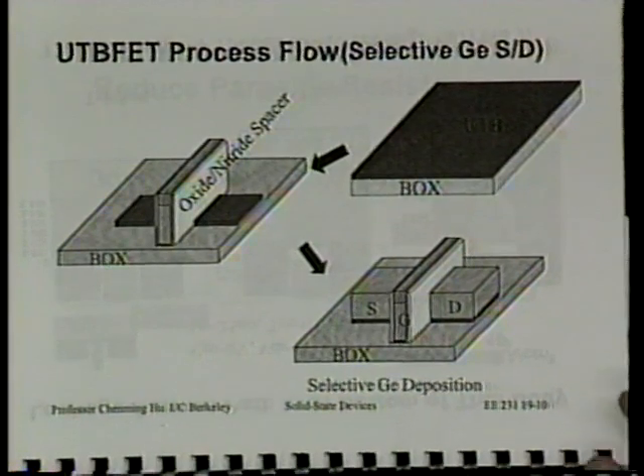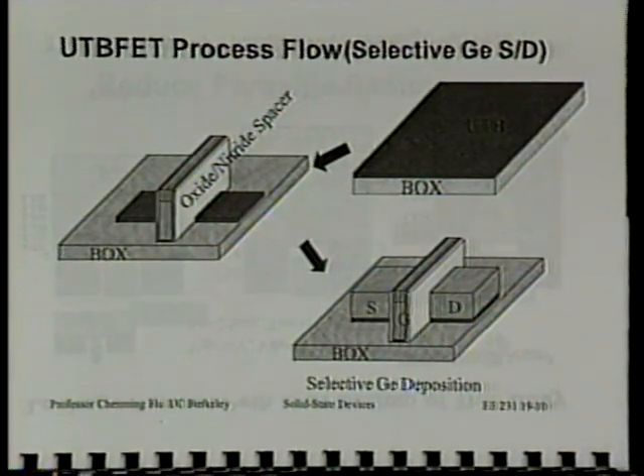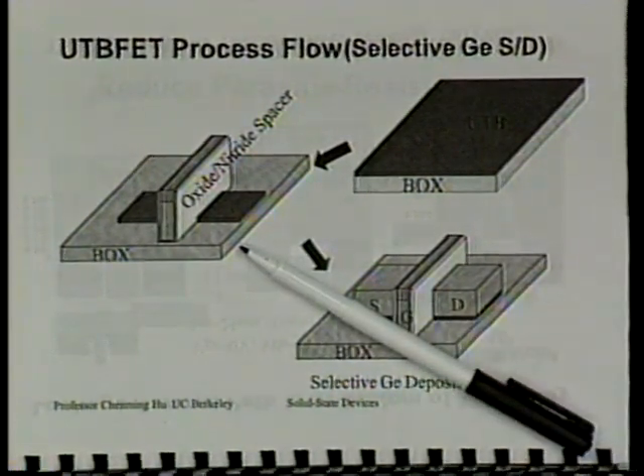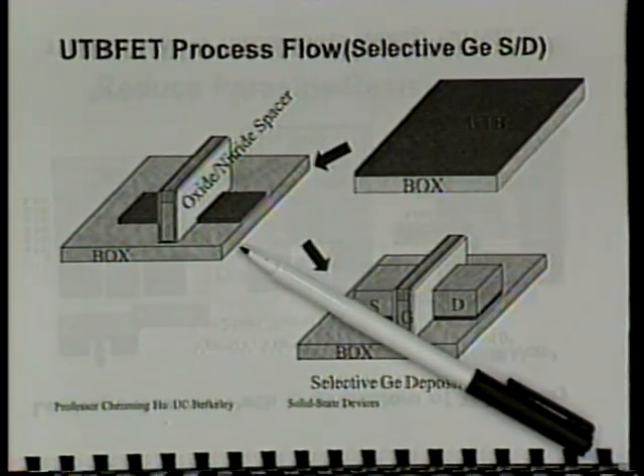So next, how do we make such a device? Young-Kyu Choi demonstrated this device. We buy the SOI material. It comes with 1,000 angstrom SOI film thickness. So we reduce this silicon thickness by successively growing some oxide and etching it away, and measure how much silicon is left. It's still too thick, so we just oxidize some more and measure how much is left. So it would take a few iterations to get to the kind of thin thickness we want. And again, this is not something we're happy with. So if you have some ideas how to make these thin silicon films other ways, those will be really breakthrough ideas. A lot of opportunities for inventive creativity here.